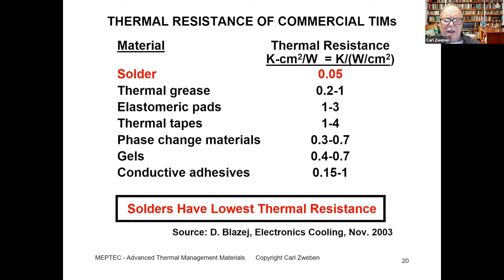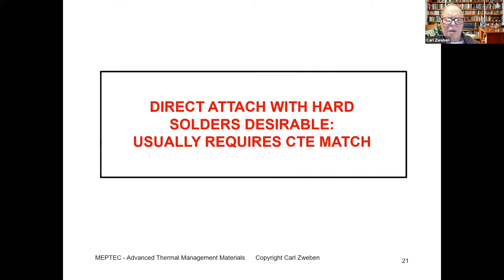If we look at compliant thermal interface materials and solders, here we have the thermal resistance. This is a somewhat old paper from D. Blazej, but the results are still pretty much the same, that solders have the lowest thermal resistance compared to the polymeric TIMs. So the bottom line, or takeaway, is that we would like to use direct attach with hard solders to minimize the thermal resistance, but that usually requires a CTE match. Otherwise, you get high stresses.